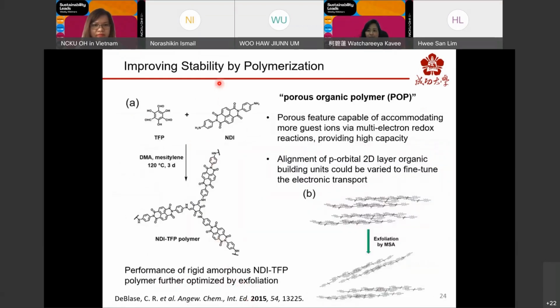Now, one of the strategies to alleviate this dissolution issue of organic materials is polymerization. And we have also extended our study to a family of porous polymeric materials. The porous frameworks are expected to be capable of accommodating more guest ions via multi-electron redox reaction, thus providing high capacity. The alignment of the p orbital to the layered organic building unit could also be varied to fine-tune the electronic transport in the structure. And so the porous organic polymer, POP, condensed from the NDI and TFP, has been prepared in our group and used as cathode material for sodium-ion batteries.